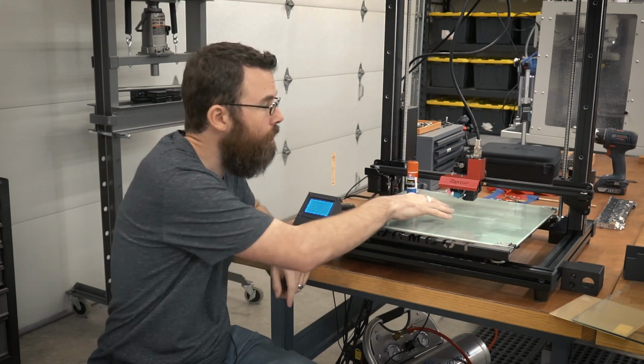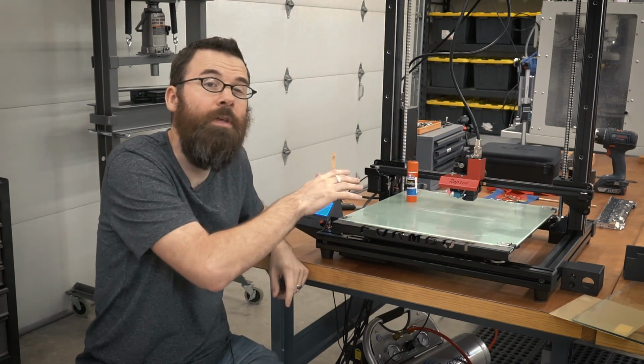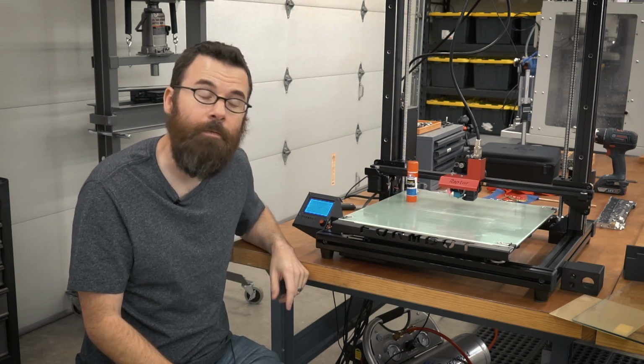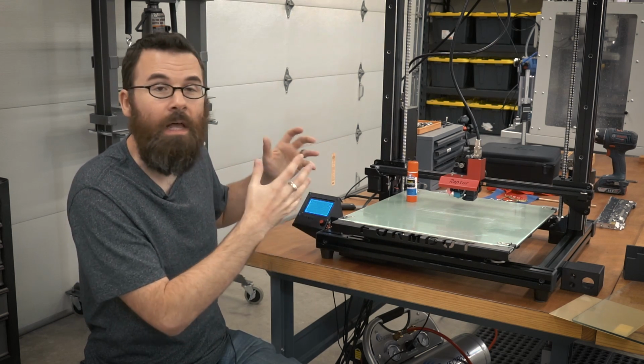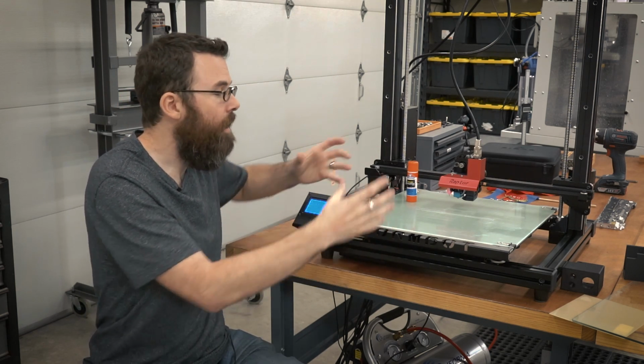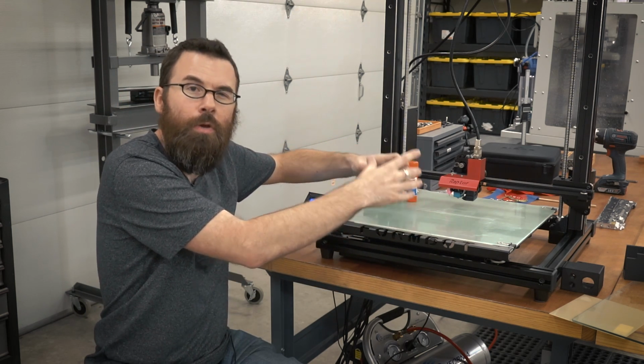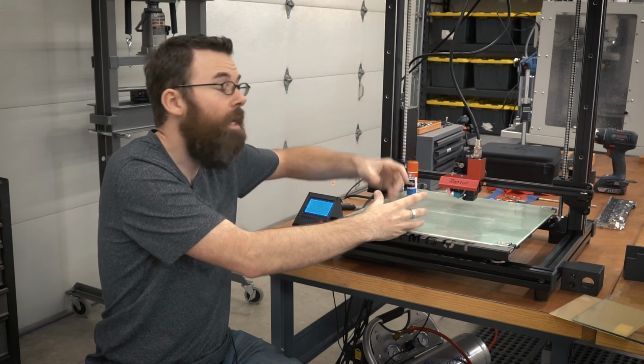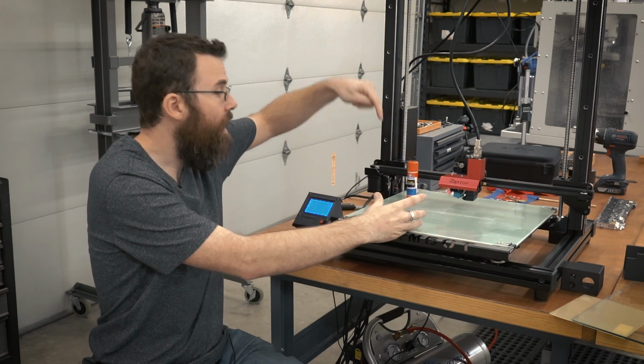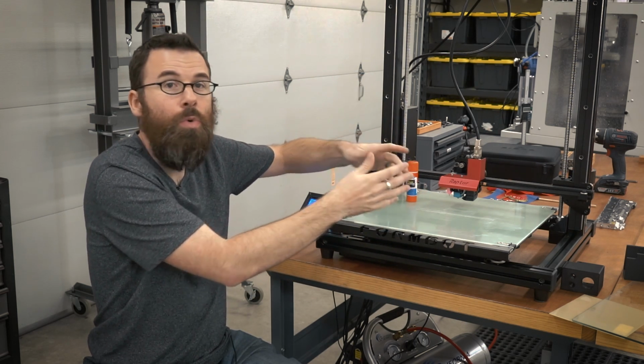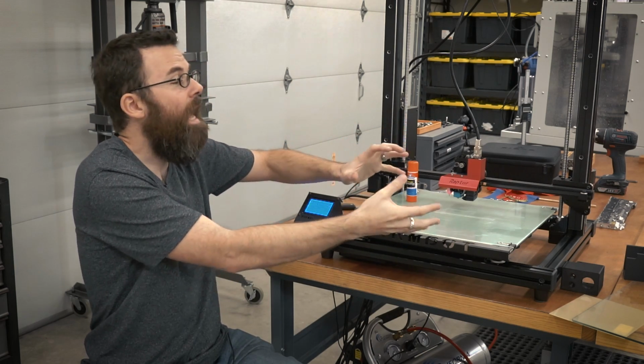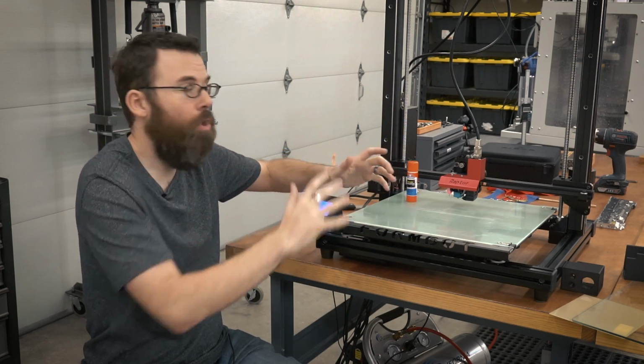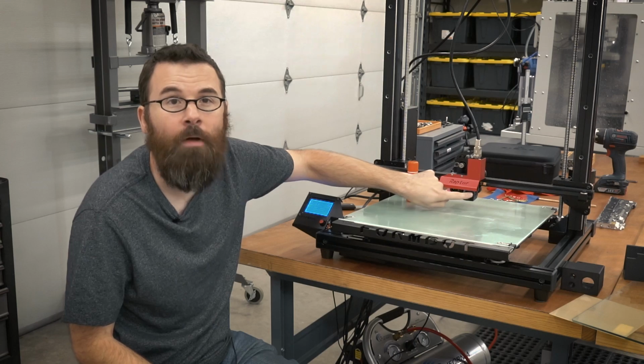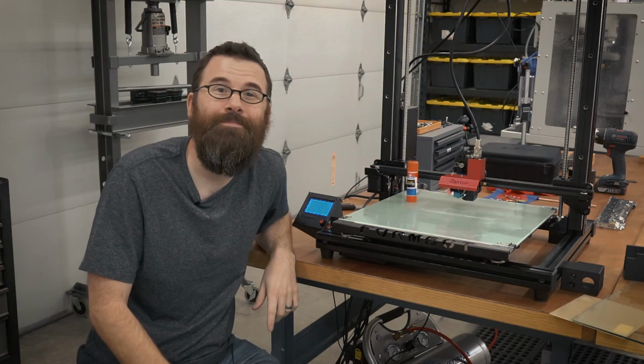The other thing you're going to want to know is if you have a layer cooling fan, you're going to want to turn that off. What happens with a nylon X or a nylon type material is you have the very warm bed, you have the relatively hot component, and obviously the very hot filament. If you lay that down and then instantly cool it, you're not going to get that layer adhesion, and that's when you're going to get all the warping and curling. So be sure to turn off your layer cooling fan.